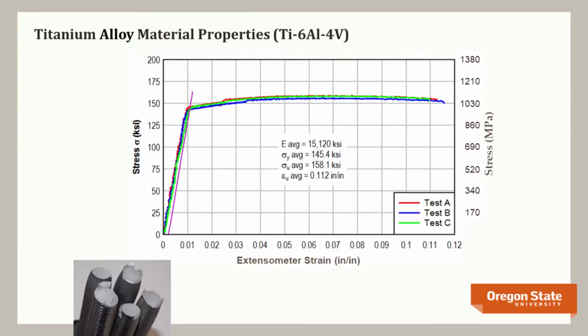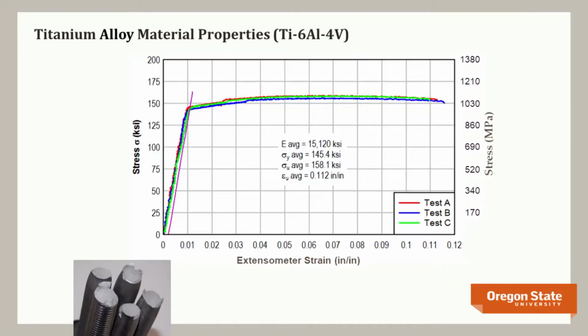So here's a typical stress strain plot for the titanium alloy bars that we're using. You can see it's elastic until we reach yield. We don't have a well-defined yield point, so we're using a 0.2% offset to define yield. But yield for this material is in the neighborhood of 140 KSI, the real yield strength. The specified yield strength is 130 KSI. You can see that the elongation out here is about 11% elongation, more than 11% elongation. So it's high strength, but with ductility. Young's modulus is about half that of steel, a little more than half. And in general, pretty good behavior.